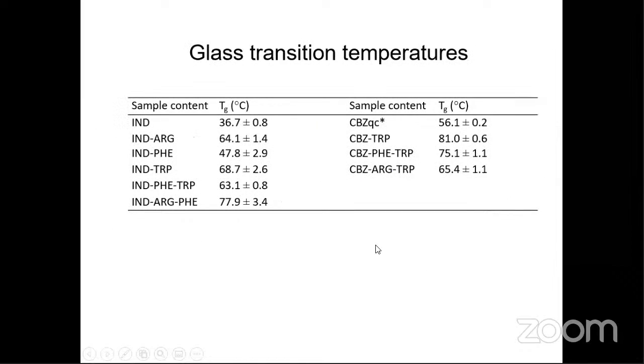Then we continue to use DSC trying to figure out the TG information. The pure indomethacin TG is around 36, and carbamazepine 55, and the coamorphous samples showed much higher TG compared to the pure compound - much higher, and basically this is very good.